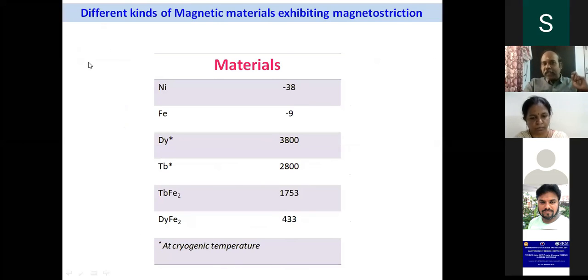So when we compare the different kinds of magnetic materials, as I told you in my first slide itself, all the ferromagnetic materials show magnetostriction to some extent. When you see the magnetostrictive component from different kinds of materials, the simple nickel shows around -38, iron shows -9. But if you see the rare earths, particularly the lanthanide series, dysprosium and terbium, they show a huge value of around 3800, 2800, etc. But the problem is their ordering temperatures are much less than room temperature, so they are not practically applicable for any room temperature application.